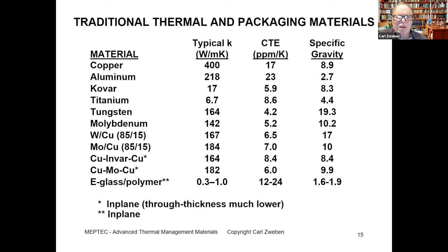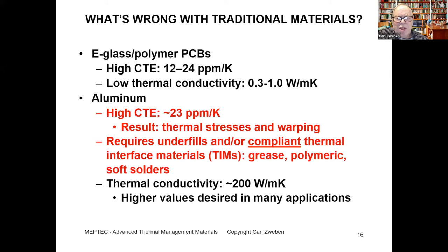So here we have a chart of traditional thermal management materials. We have copper and aluminum at the top, and they have pretty good thermal conductivities, but as we'll see, they have high CTEs. And then we have a range of materials, traditional materials with low CTEs, but they have thermal conductivities no better than aluminum. And finally, we have e-glass polymer printed circuit boards, and they have relatively high CTEs. Again, the range of CTE properties that I find in handbooks and papers ranges from 12 to 24 parts per million per degree Kelvin. In addition, these materials are pretty much thermal insulators, with thermal conductivities in the range of 0.3 to 1 watt per meter Kelvin. So let's look at aluminum.